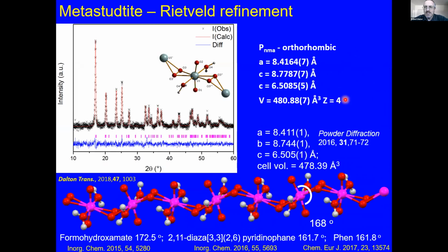We've always used powder XRD to check purity, but eventually we found somebody to do Rietveld refinements. And what was really interesting from metastudtite is that it seems very happy to bend the uranyl. Now, I said earlier that the uranyl ion is covalent, so bending a UO double bond is really quite tricky, and there are very few examples in the literature where this has happened. But we see from our refinement that the bend is about 168 degrees, so quite far away from linearity.